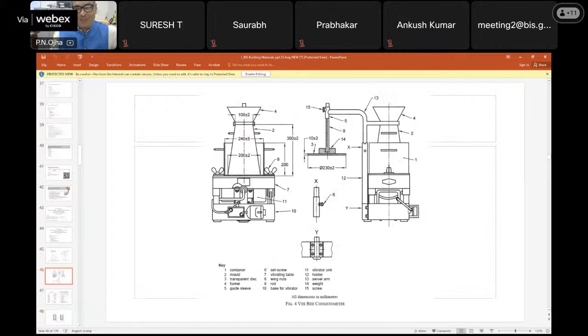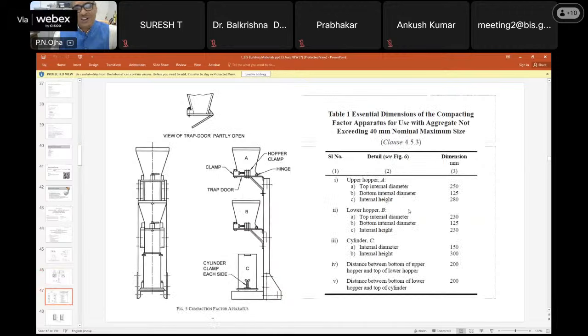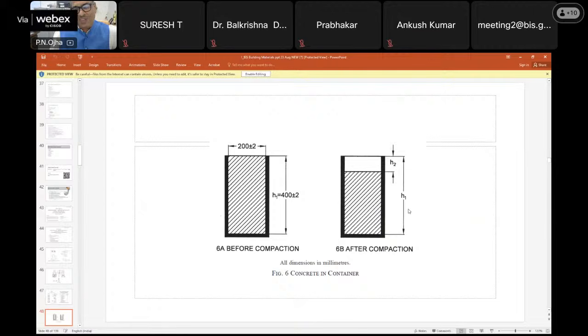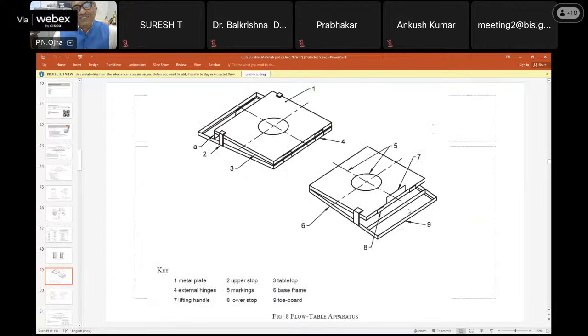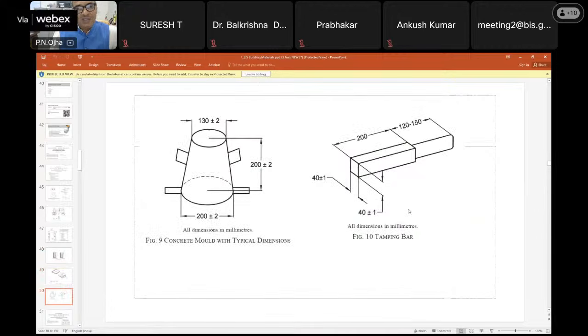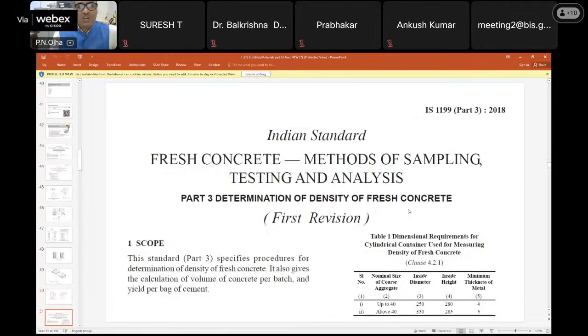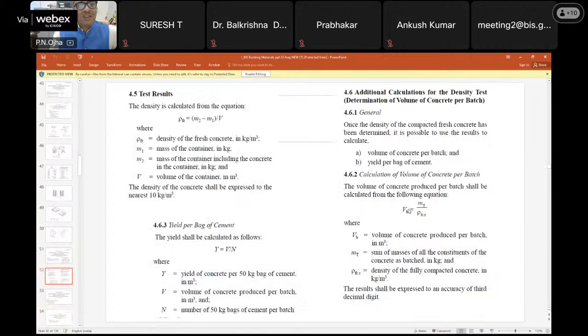Okay. So this is a VB consistometer. When the concrete doesn't have a flowable property, being dry, almost dry in nature, the slump test is not a valid test. So we test it on the VB consistometer. And this is a compaction factor test. Normally these tests are not being used nowadays. This is concrete in a container. This is before compaction and after compaction. This is the bleeding test. This is the flow table test, we call it flow on the table, in the case of self-compacting concrete.